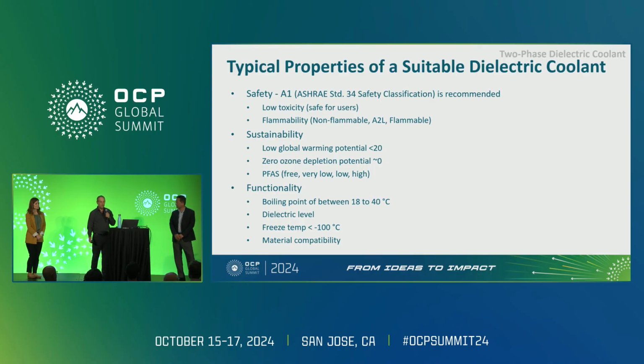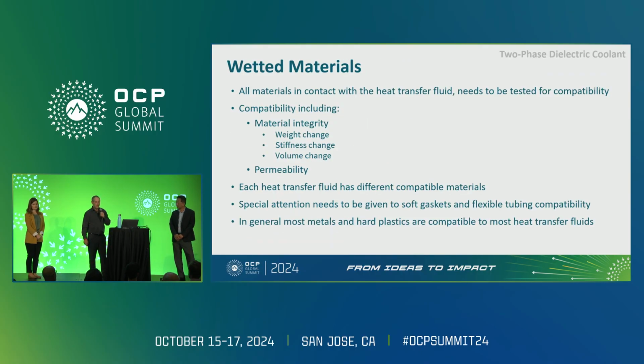And then we move to the next topic of material compatibility. That is a little bit more complicated in these liquids because material compatibility is different per liquid. Each liquid attacks different materials in the sealing and in the tubing. So for every material you want to use, you'll have to retest for material compatibility. When we talk about material compatibility, it is testing and making sure that, for example, with a seal, there's no weight change, the stiffness of the O-rings doesn't change, and the volume doesn't change. Those are the tests we're doing.